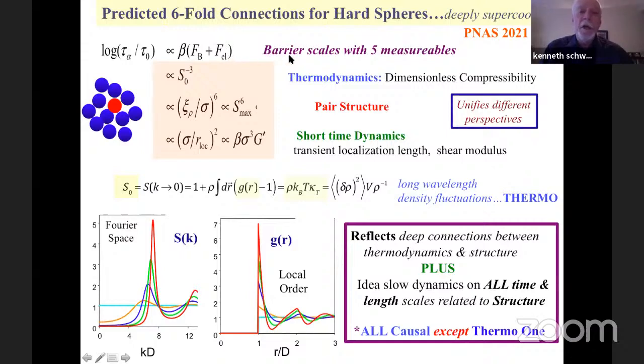But because it's a microscopic theory, we've been able to establish that the barrier scales with 5 other experimentally measurable quantities. The barrier scales as the inverse 3rd power of the dimensionless compressibility, which is a thermodynamic property. It's a theorem that it's the long wavelength value of the structure factor, related to the integral of g(r) minus 1, equal to the isothermal compressibility, equal to the mean squared amplitude of density fluctuations. So the theory predicts there is a connection to thermodynamics, even though the theory is not formulated at all in terms of a thermodynamic scenario. The theory predicts that the barrier scales as 6 powers of the static correlation length of g(r) in real space and 6 powers of the Fourier space order parameter, the peak of S(q).